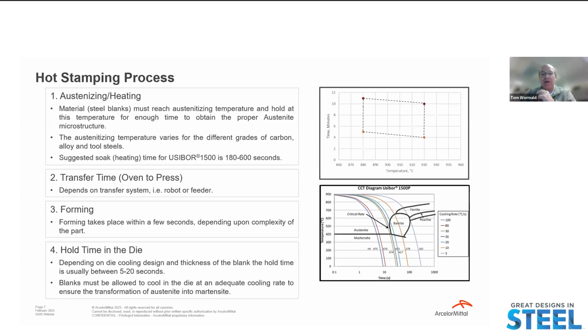A rapid cooling rate is required to ensure complete transformation to high-strength martensite by the end of the forming process. The thickness of the blank also affects hot stamping, as a thicker blank logically will retain heat and influence many of the factors we just discussed.